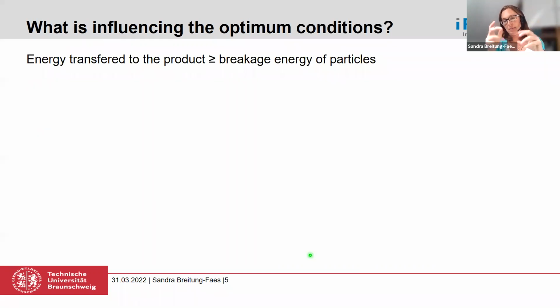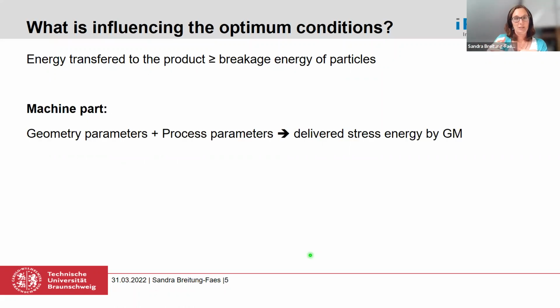So first, my basic idea was to say, okay, I need at least two energy values I can compare somehow. On the one hand side, I need the energy which is really transferred to the product, which is a function of the suspension, of the process parameters, and also of the product material. And this energy needs to be at minimum equal to or even a bit higher than the breakage energy of the particles themselves. So I thought about first, what do I need as machine parameters? I have the process parameters for sure. We talked about them. They are included in the original stress model.